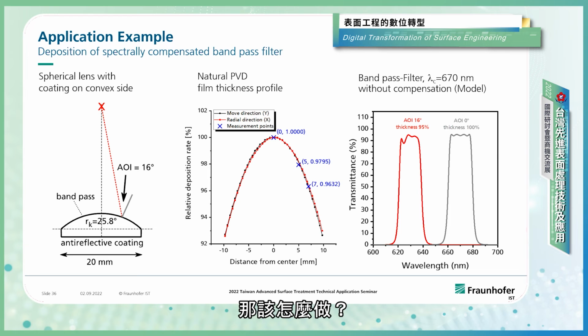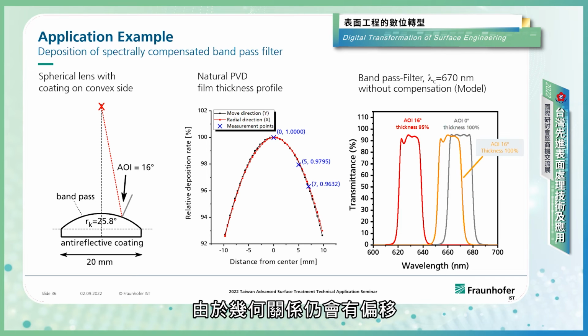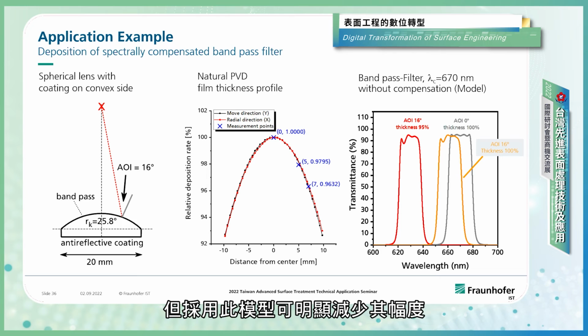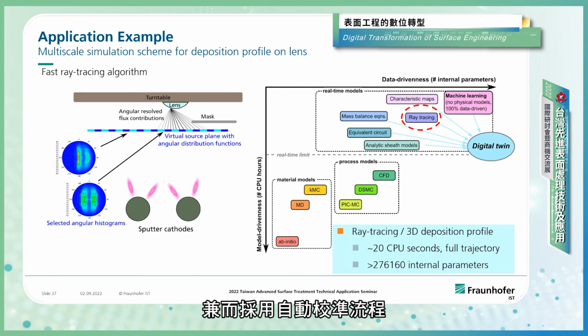How can we do this? If we recalculate with the thickness, we can see there's a significantly smaller shift due to the geometry. There will be a shift, but it can be significantly reduced by applying the model and by having an automated corrected process. We want to be in the real-time mode, so we need something fast.